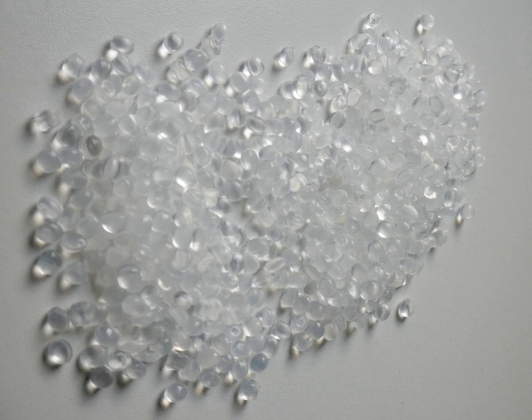Topic: polyethylene with multimodal molecular weight distribution. Polyethylene with multimodal molecular weight distribution consists of several polymer fractions, which are homogeneously mixed. Such polyethylene types offer extremely high stiffness, toughness, strength, stress crack resistance and an increased crack propagation resistance. They consist of equal proportions of higher and lower molecular weight polymer fractions. The lower molecular weight units crystallize easier and relax faster. The higher molecular weight fractions form linking molecules between crystallites, thereby increasing toughness and stress crack resistance. Polyethylene with multimodal molecular weight distribution can be prepared either in two-stage reactors, by catalysts with two different active centers on a carrier, or by blending in extruders.